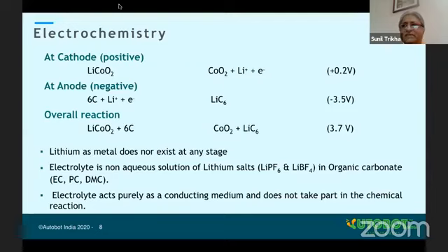So here lithium is not making a compound like lead sulfate. The lithium is loosely held in the compound between two layers of metal oxides. So the main advantage is there is no lithium metal in the reaction, only lithium ions which are present. Number two, there is no reaction of electrolyte materials. So the electrolyte only provides a carrier for lithium ions.